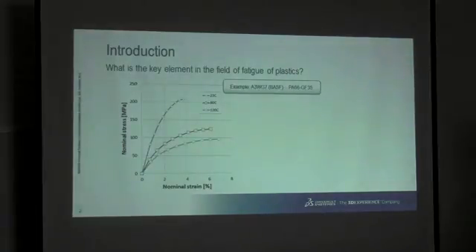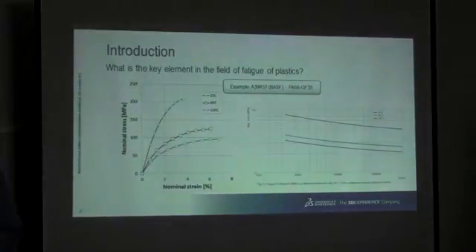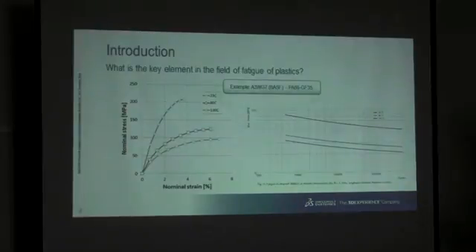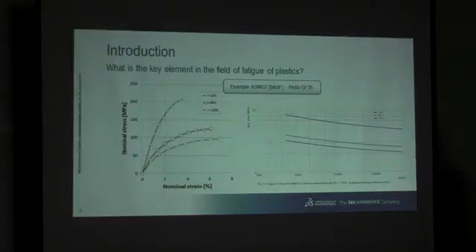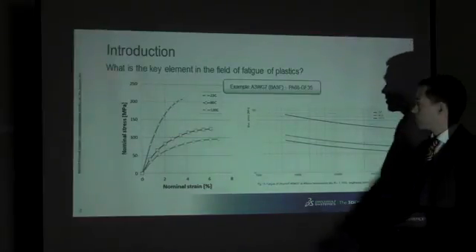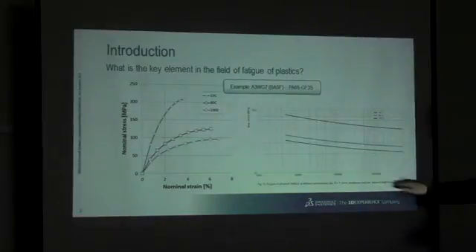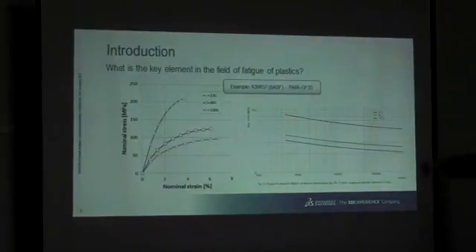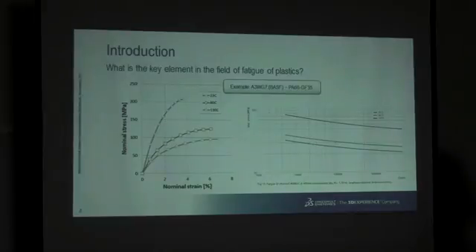What's interesting? Well, if you draw a parallel to SN, or nominal SN fatigue properties, which is not accepted, but it's industry practice, it's what's being done. Then you have, again, reversed stress amplitude on this axis and the life on this axis for the same material. And you can see the enormous drop depending on temperature. And this is just getting warmed up. We're going to see a lot more interesting. So temperature, interestingly enough, proves to be key.